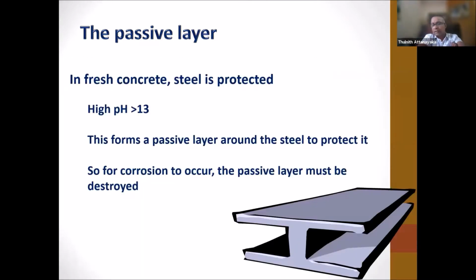This is the key point when it comes to reinforced concrete: the passive layer. In fresh concrete, the steel is protected because it has a high pH value of more than 13. This forms a passive layer around the steel to protect it. As designers, we design for a concrete cover like 30 millimeter, 50 millimeter for water retaining structures and all. The newly poured fresh concrete has a high pH, and that is the protection we get from concrete for the steel.